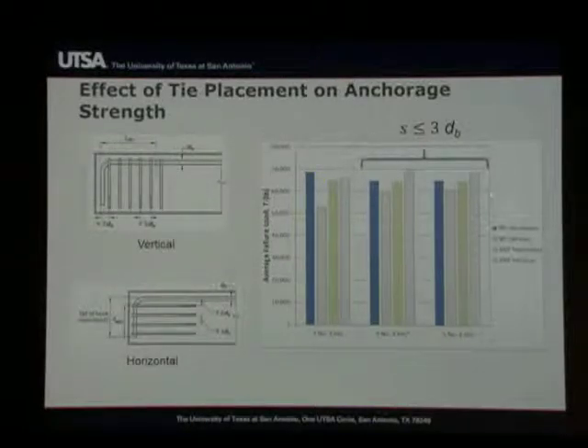And you see that the lines on the right tend to be pretty even. So again, when you put a lot of transverse reinforcement, it seems that the orientation doesn't matter. When you put a very light amount of transverse reinforcement, not meeting the 3 db requirement in the code, then you start to see more differences. For example, in the 90-degree hooks, it becomes clear that placing the hooks in the horizontal orientation is more advantageous than placing it in the vertical orientation. It is the tendency of those bars to prevent the tail end of the hook from popping out.